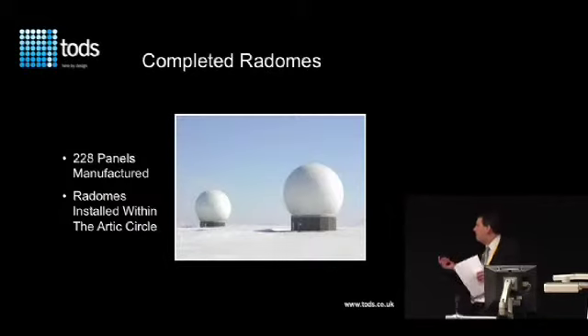I think it's fair to say, particularly about mould tools for any of these processes, you really need to start from scratch. For the radomes, we used to use moulds with bushes so we could actually drill in mould. Well, as soon as you've got holes in your mould, you're struggling with vacuum. So we took the principle that we would do monolithic moulds and have separate drill jigs, which works very well. There was a total of 228 panels, which the radomes were installed within the Arctic Circle. We also found that because of the quality of the process, the dome actually fitted together better. With hand lamination, you do get slight variations in curvature, etc. This actually is the best dome that we've ever done.